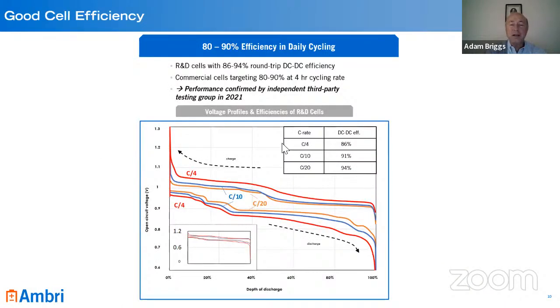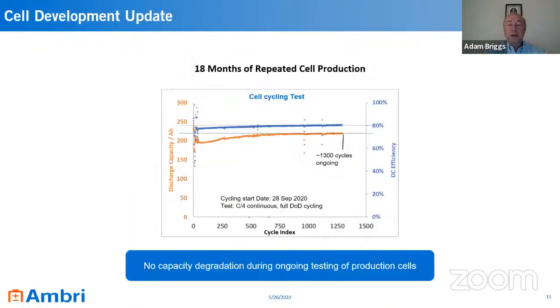And so here's some performance data associated with how these cells perform. Again, C/4 means that you're operating at a power to result in a 4-hour charge or a 4-hour discharge. So C/10 means 10 hours, C/20 means 20 hours. You see the efficiency ranges from 94% to 86% across that power range. Here are the shapes of the voltage curve. You can see this goes from about 1.2 volts down to about 0.6 volts at the bottom of discharging. And otherwise, very similar to other battery systems, as you probably have seen. And again, been making these particular cells for about 18 months.